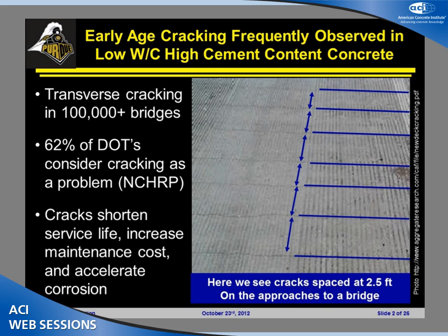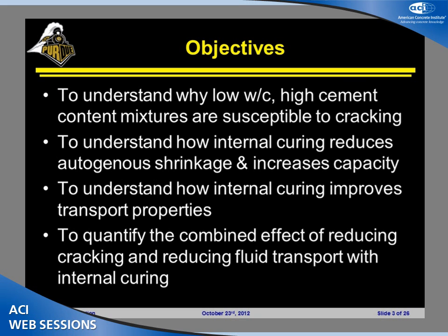So the question is, can we do something early on to get substantially more service life out of the decks that we're looking at? What I want to do today is hit four main points. I want to understand why the low water to cement ratio, higher cement content mixtures may be more susceptible to cracking. These are the high performance concretes we're talking about. And we want to understand how this can be combined with internal curing to reduce this cracking potential, especially at the very early ages.